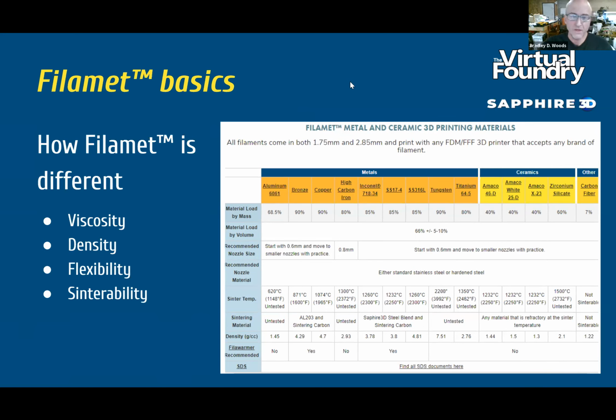Sure. So the key difference is that it's with different interesting materials. Things most frequently are the metal powder. So essentially, people tend to picture a plastic filament with some metal in it. But when you get right down to it with a microscope, it's kind of the other way around. It's metal powder with just enough plastic coating the outside of it to stick them together into a string for filament, so that it's strong enough to get through the 3D printer.